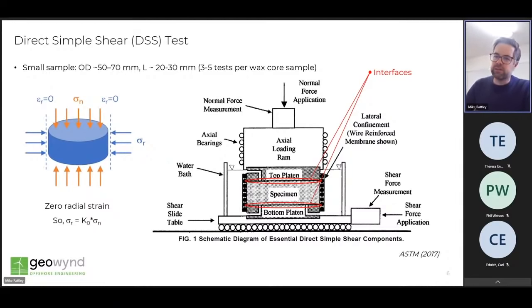One important aspect of the test setup are the interfaces placed at the top and bottom of the sample, as indicated here. Those are there to prevent slippage between the soil and the loading platens of the apparatus during shear, and their selection can have a pretty significant impact on the measured response, so it's important to understand a bit about those.